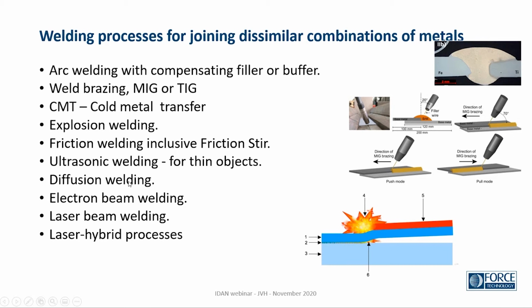Diffusion welding, again, a very special technique where you have very smooth surfaces, very clean surfaces, pressed together and increase temperature. At a certain level of temperature, atoms would jump from one side to the other, and that way we will have a weld. It takes vacuum, and it takes high temperature, and it takes time. So I think this is a research technique. I've seen very few examples of this kind.